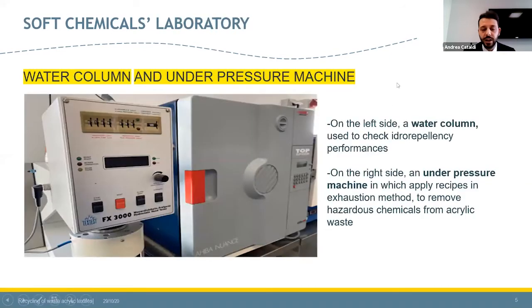Okay, these two machines are actually the most important for the previous part of the project, in order to understand if we are working in a good way. So we have a water column in the left part of the picture and an under-pressure machine on the right part. The water column is used to check hydrophobicity performances, and just a little explanation for those who have never seen a water column: it is an instrument that helps to do a dynamic test, a dynamic method. This instrument contains an electronically controlled pump, which produces the test pressure in an internal water tank in the lower part of the machine. The tank is linked to a test head, where in this case the wasted acrylic and then the acrylic can be located. After the test has been started, the test pressure is automatically controlled.